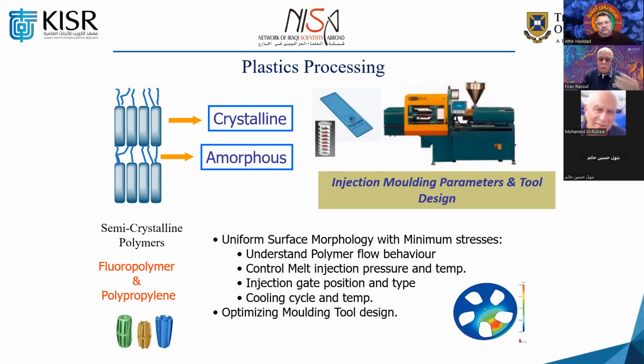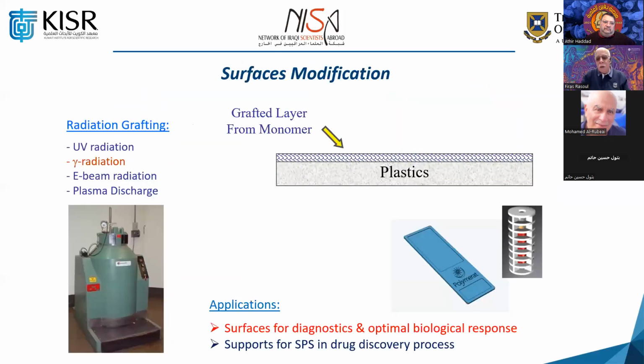of the plastics. And the plastics we are using, as I mentioned, are fluorinated polymers like PTFE and others, and also polypropylene. We found that polypropylene is probably much easier to handle. It is easier to process, while Teflon sometimes is very tricky. It requires a higher temperature. Grafting onto Teflon is extremely challenging.